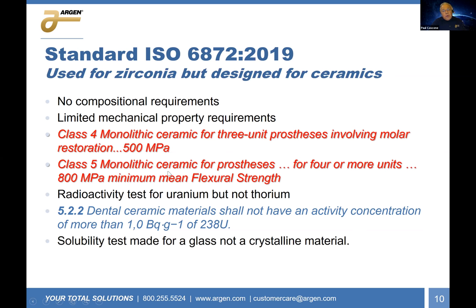For class five, where we have 4 or more units, and this can go to a 14-unit bridge, 800 megapascals doesn't cut it. 800 megapascals is barely enough in our estimation for a 3-unit restoration, okay? The other problem with the standard is that the radioactivity test was made for uranium, but it doesn't include thorium. Now, I showed you specifically that the zirconia sand has that thorium radioactivity in it, and it's in there in a significant quantity. But the reason why it doesn't address thorium is because, when it was designed for dental porcelains, uranium dioxide was used very long ago as a fluorescing agent. Now, that material was eliminated in the 70s, but still, they kept this radioactive concentration.